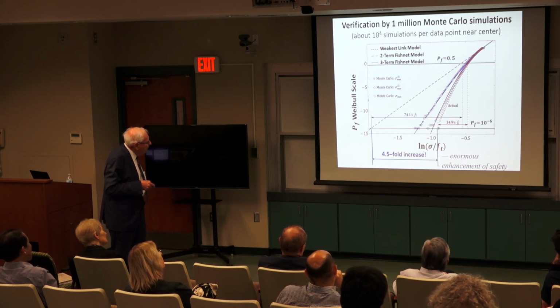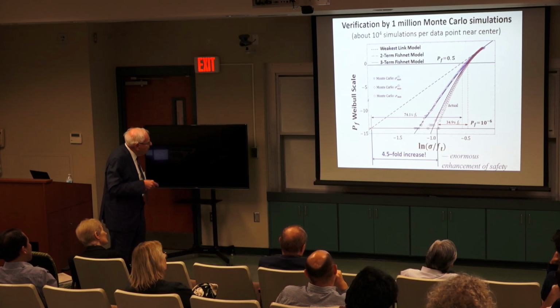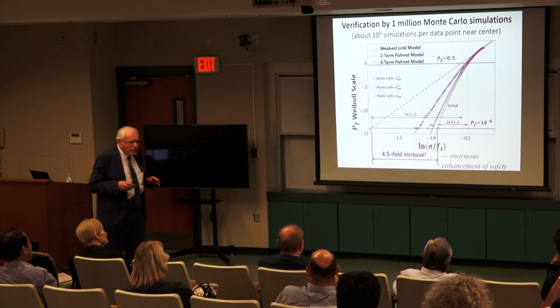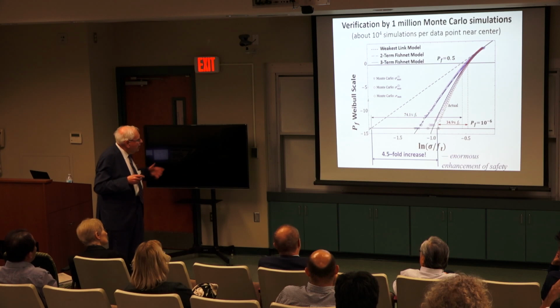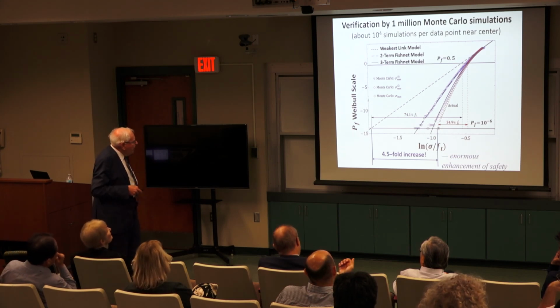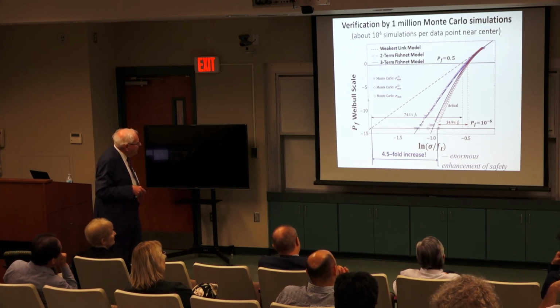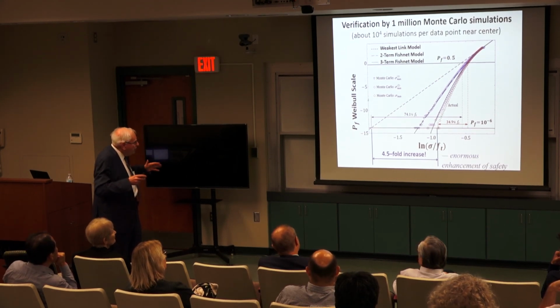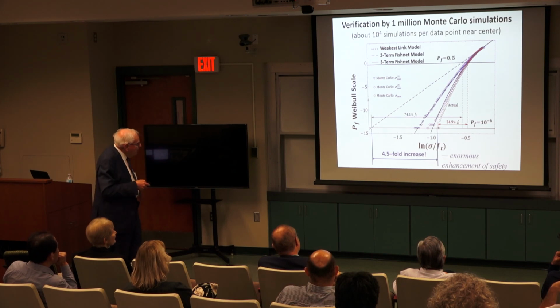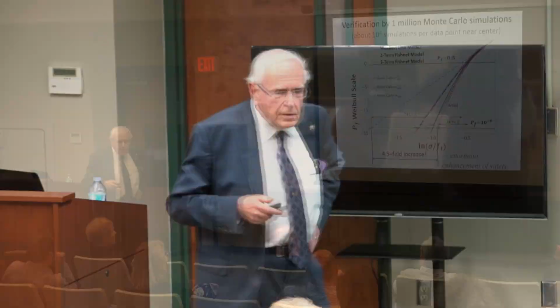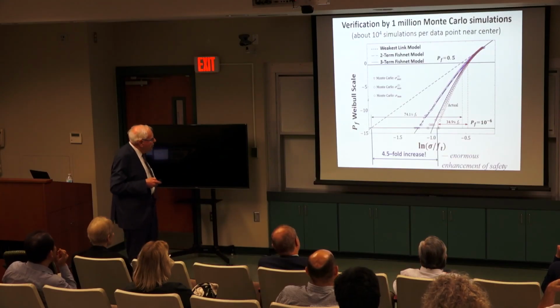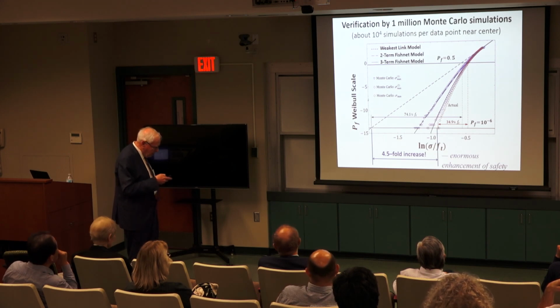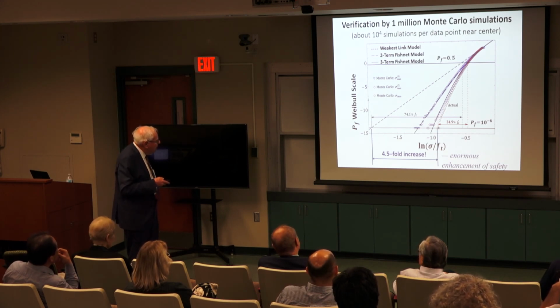So it's very smooth. It's virtually the exact probability distribution. So this is the analytic 2-term fishnet. This is simulation. It means we exclude all failures where more than 2 links failed. And then this is the 3-term fishnet. It matches very well. If you let any number of failures occur before overall failure, you get this line. You see how close it is? For most practical purposes, it's good enough. So we cannot actually get an exact analytical solution for any number of failures, but we get very close analytically, and in a simple way.